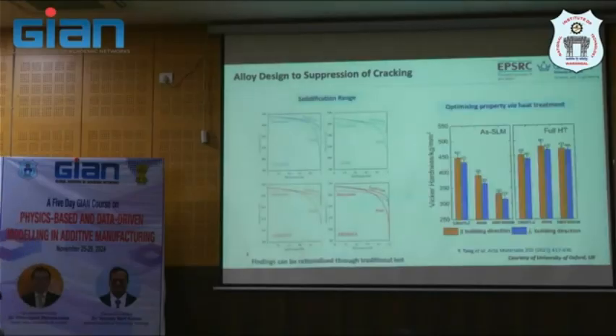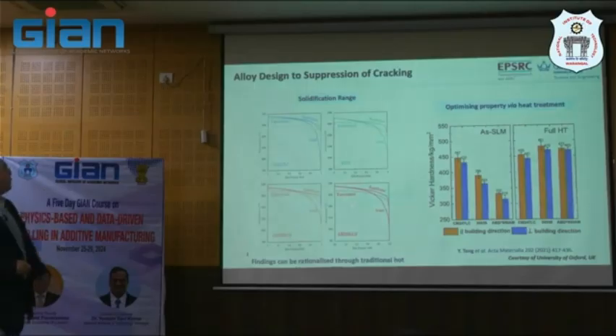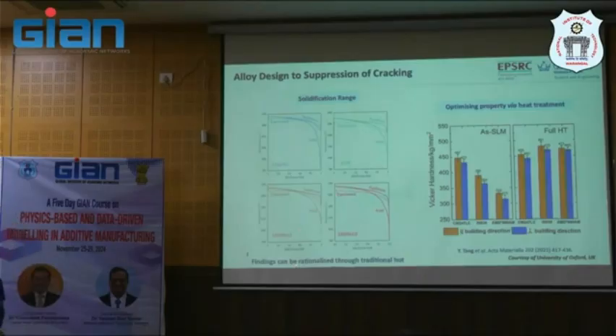It's not just printable and crack-free, but if we confirm with the solidification range here, when we compare with the chart, which is the non-equilibrium and equilibrium calculation, I mean, we use thermal calculation to compare, calibrate and verify. You will see that the new superalloy actually has a very minimum freezing range, compared with CM247 and the 939 here. And that's why this finding is rationalized through the traditional hot cracking approach.